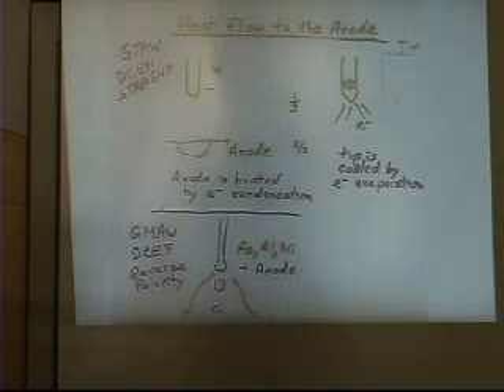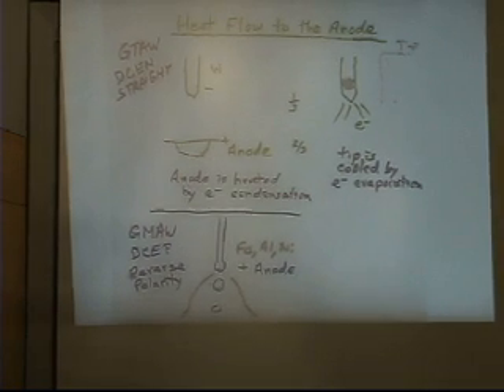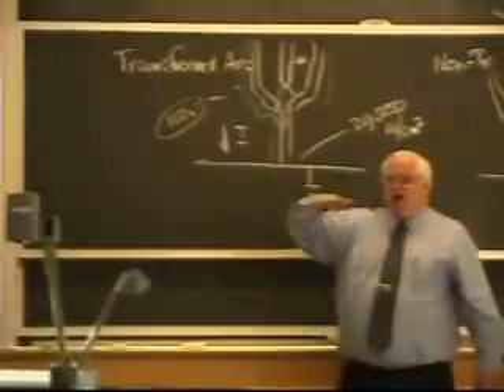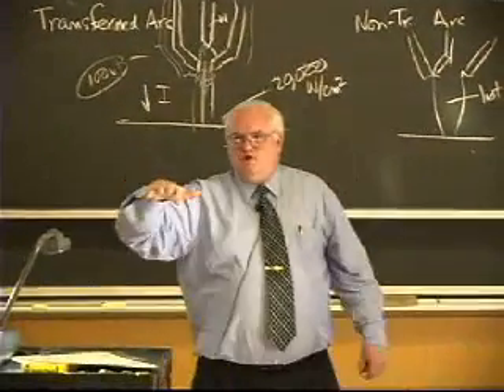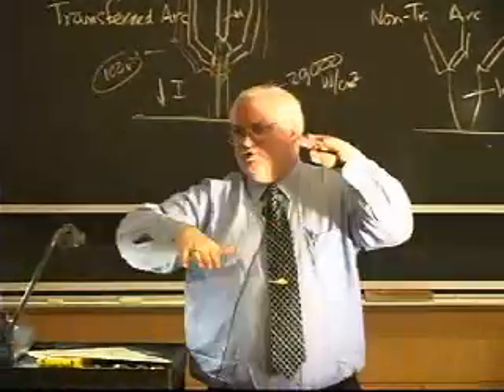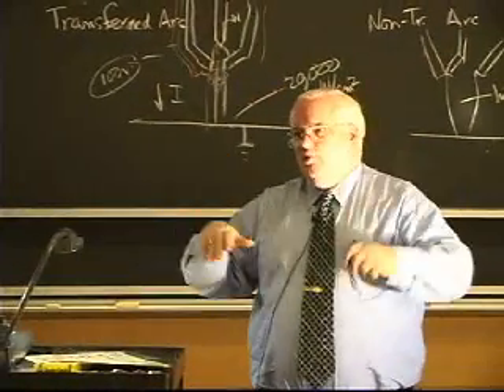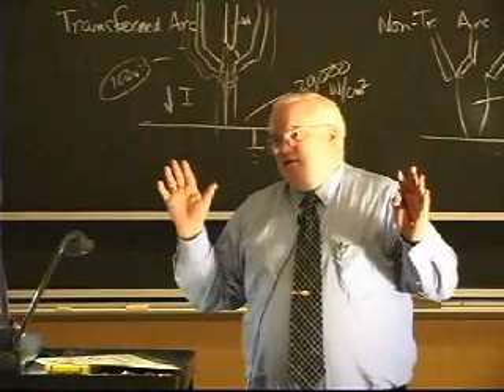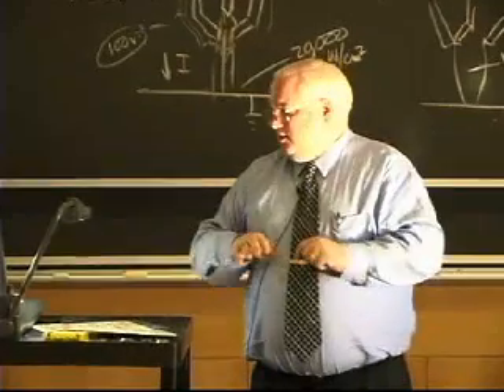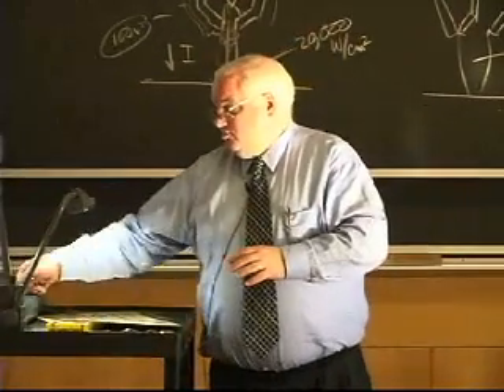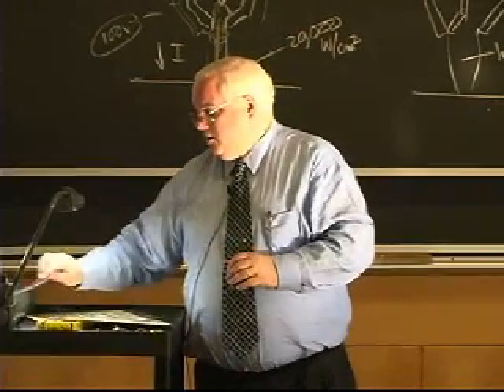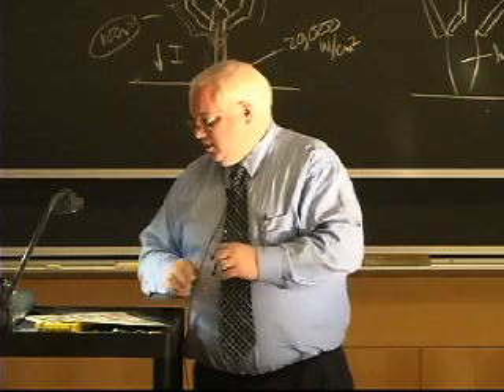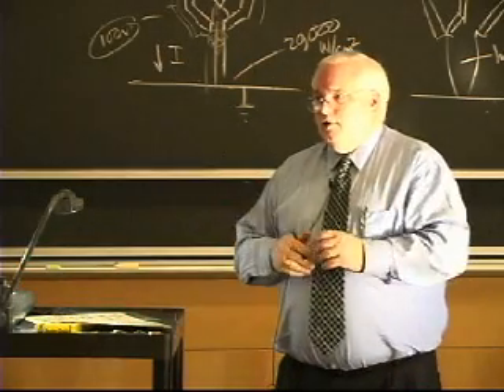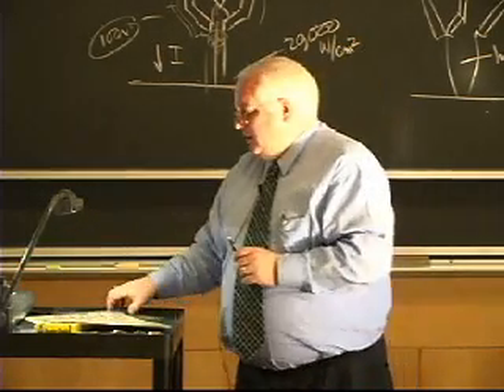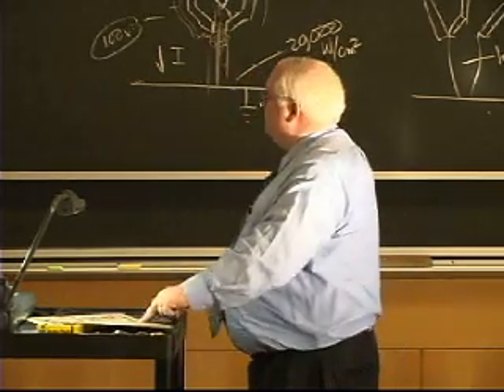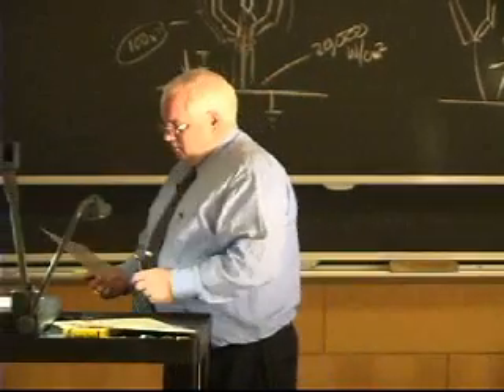And so what people have done is they built special types of transformers that essentially balance out that DC. So you put a different voltage on the positive pulse than you do on the negative pulse of your AC welding. They call it variable polarity plasma arc welding, and with variable polarity plasma arc, if you're willing to pay $50,000 for a power supply, you can get beautiful welds, and NASA does. Okay, when they're making space shuttle main tanks, they don't do that a whole lot anymore.